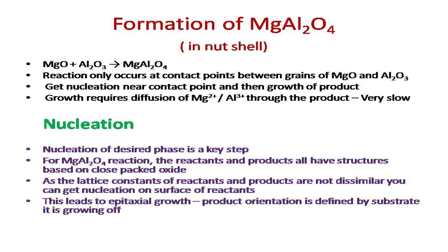Now looking at nucleation, which is the main thing through which this reaction takes place, nucleation of the desired phase is a key step. For the MgAl2O4 reaction, the reactants and products all have structures based on close packed oxides. As the lattice constants of the reactants and products are not dissimilar, you can get nucleation on the surface of the reactants. This leads to epitaxial growth, that is, product orientation is defined by the substrate it's growing off. That is how it proceeds from the interface, which is continuously moving on both sides of the picture you have seen. So it is this nucleation that determines the growth of the layer.